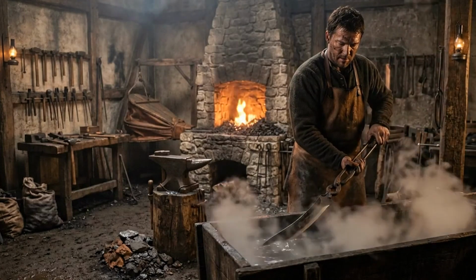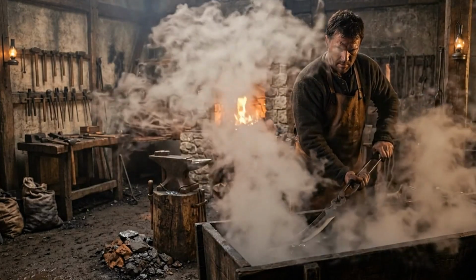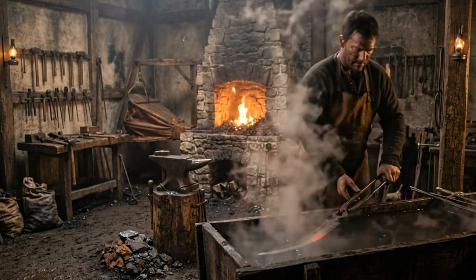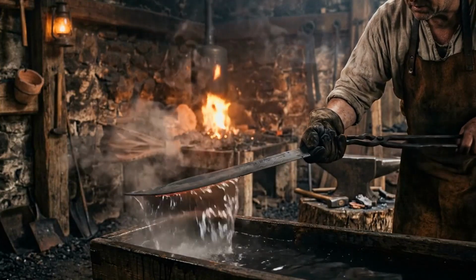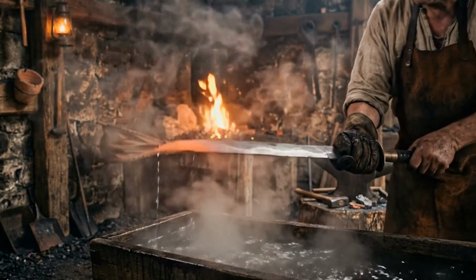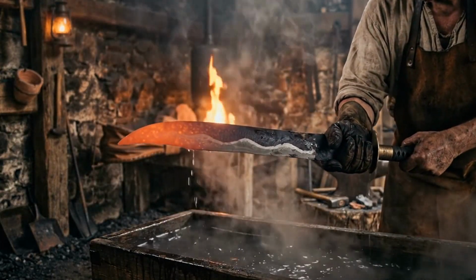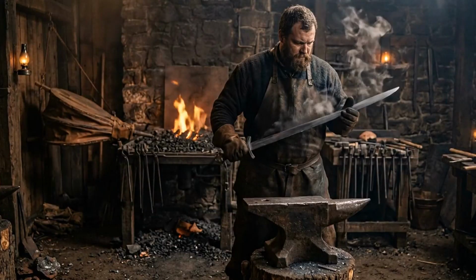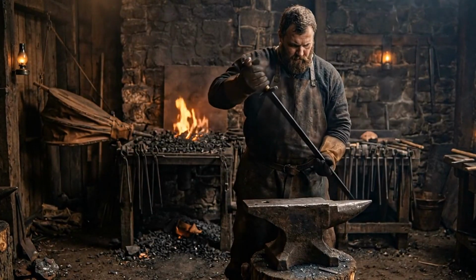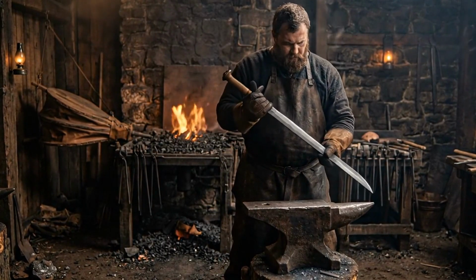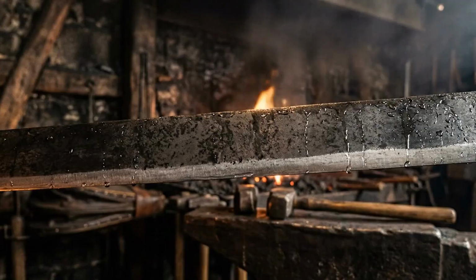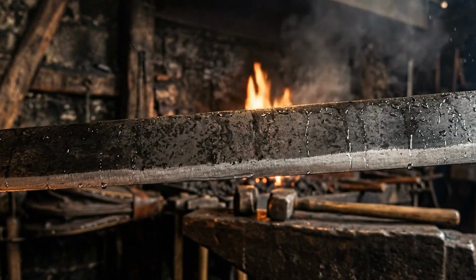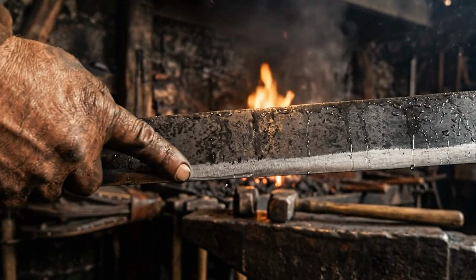The thin clay along the cutting edge allowed the steel to cool rapidly, converting it to martensite, an extremely hard crystalline structure that gave the edge its ability to take and hold a razor sharpness. The thick clay over the spine slowed the cooling rate dramatically, preventing martensitic transformation and leaving the spine in a softer, tougher pearlitic or bainitic state.